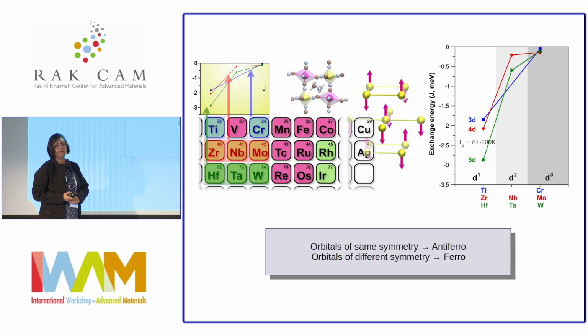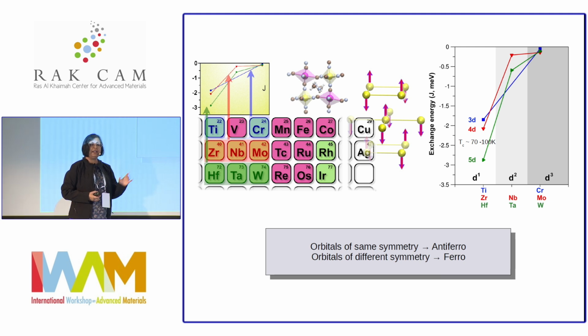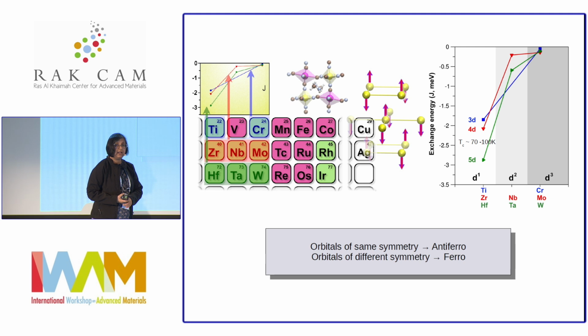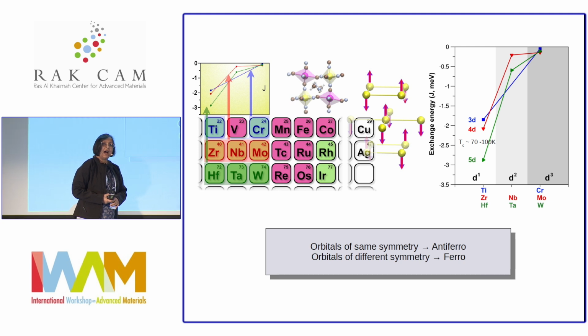Have you compared the stability of those to copper metal? Yes. My immediate concern was that zirconium iodide... We didn't show you, but we did consider their stability with respect to the copper metal. So we checked their thermal stability with respect to copper metal and others, as well as the dynamical stability, which we did not show. But we don't know what the other competing phases will be if you start making them. So we really need to have input from the people making it.